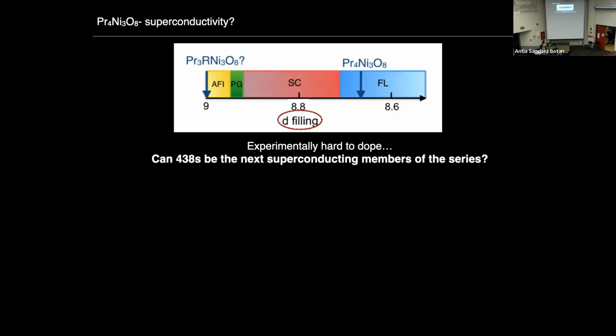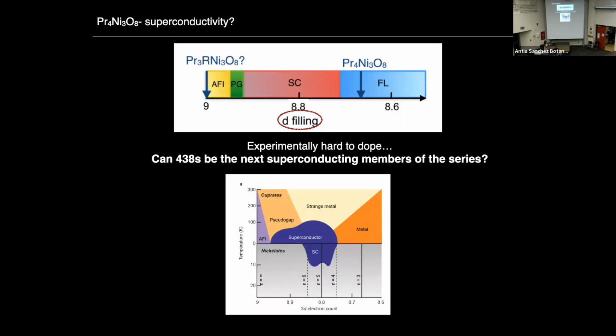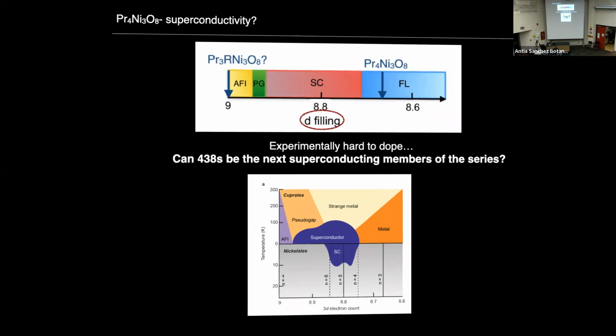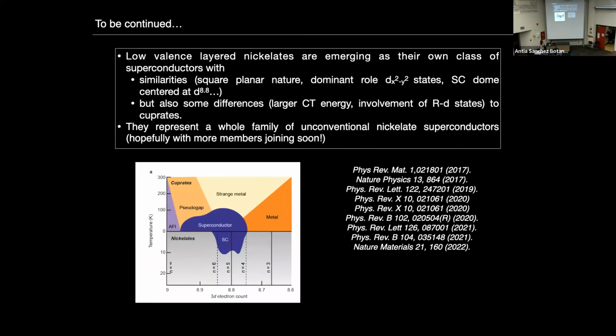And what went off is that it turned out that experimentally it was very hard to dope these materials. But I think that the discovery now of superconductivity, not only in the infinite layer compound, but also in the 5-layer compound, could perhaps bring renewed energies to try the doping of these systems a little harder. And who knows, they may just be the next superconducting members of the series, or at least that's the hope. Even if that were not to work, it's not all lost. One could also try the 6-layer or the 4-layer members of the series that you see here in dashed, because they have never been synthesized, but they will give you direct access to the dome area of filling once again without having to dope. So again, hopefully our experimental colleagues who have been so brave all the way through will have progress on that soon as well. But for today, I have no more news on that. So I'll just stop here.